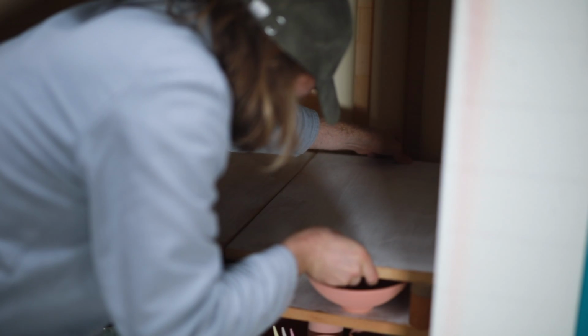Each pot is carefully placed into the gas kiln, with a few millimeters separating each one. They can't touch during this process, as if they do they'll stick forever, and the only way to unstick them is to just smash them up with a hammer. It's for this reason I have to remove all the glaze on the bases of these pots, as the raw clay itself won't stick to the shelves of the kiln.